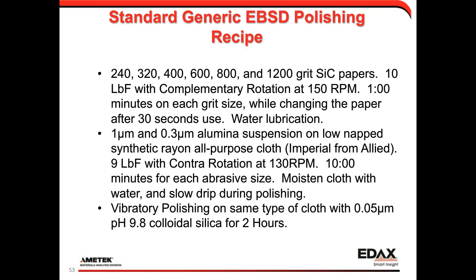Now, it's important to note that I'm using equipment where I can control the rotation speed and I can control the pressure, and that's one of the parts where we select material. It's certainly a lot easier to give a recipe where I'm giving you a very specific force to use compared to trying to hold it with your hand in place with constant force. Generally the equipment is going to work better than hand polishing for consistency. Now with this recipe, I generally use 1 minute for each grit size, but I change the paper after 30 seconds. Again, that's just to have a fresh abrasive and make it efficient. And then use water lubrication in general to keep the abrasive cool and clean.